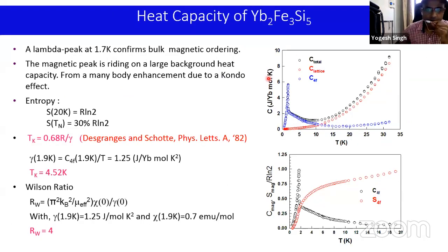The specific heat versus temperature is shown here. The black curve is the full data. The red curve is the lattice, which is the lutetium compound. And then the magnetic part is seen here in blue. The first thing to note is that there is a very large lambda-like peak, which confirms the magnetic ordering. The magnetic peak seems to be riding on a huge background magnetic heat capacity, which is most likely coming from the many-body enhancement due to the Kondo effect. We will quantify this in a moment.